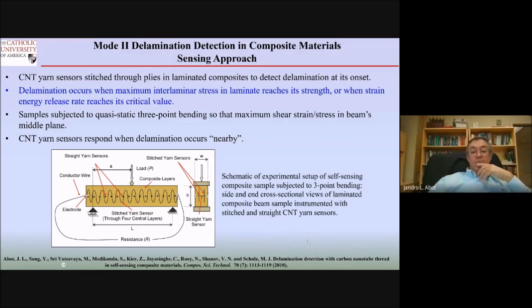So then we said, well, can we use some fibers to stitch the laminated composite material, and measure the resistance in that circuit once you form the circuit? Well, if there is some kind of damage, imagine the layers start opening up, then the fiber will be pulled. If you pull the fiber, what's going to happen? Piezoresistor response, right? So the electrical resistance will change.